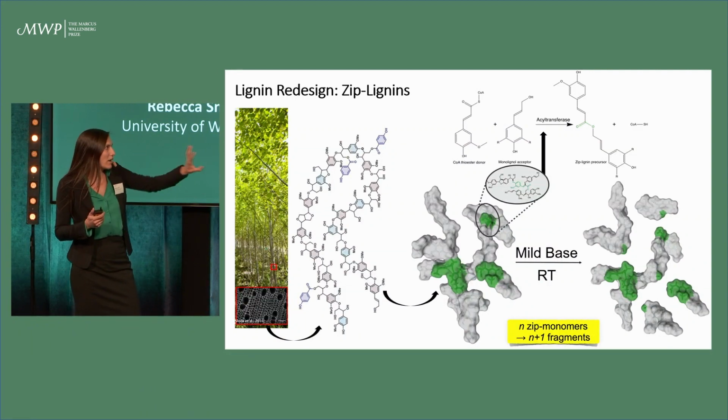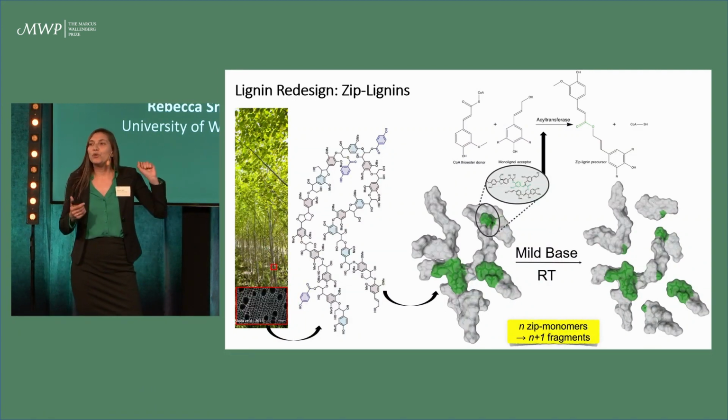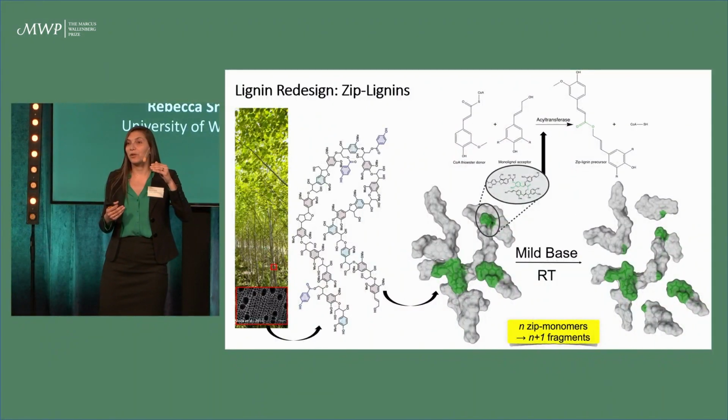If you look at this model of a poplar lignin that I have here, you can see that there are a variety of phenolic monomers that make up the polymer and also a variety of bonds that form between them. This is because the formation of lignin is chemically controlled, not enzymatically controlled. In theory, any phenolic monomer that's produced by a lignifying cell, can get into the cell wall, can be oxidized by a laccase or peroxidase, and is compatible with the chemical combinatorial mechanism of lignin polymerization, is capable of being integrated into the lignin polymer.